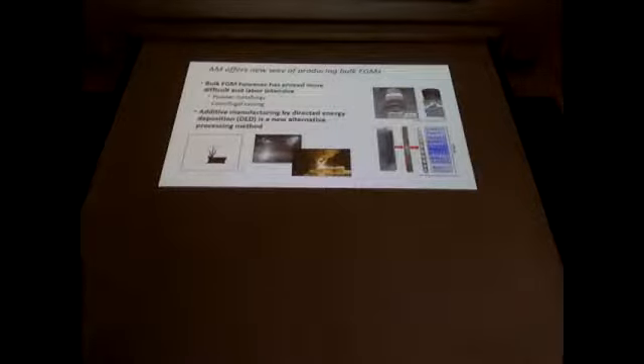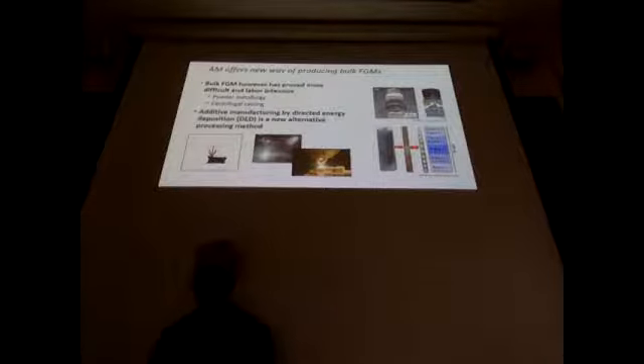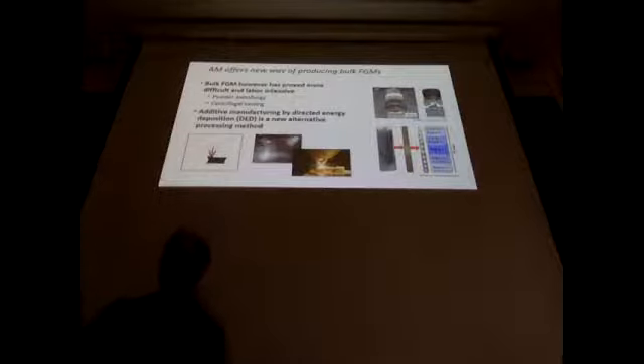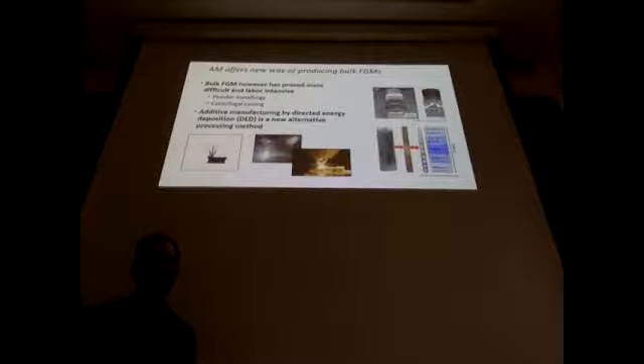So with that, additive manufacturing has become a tool to make these bulk functionally graded materials. Initially, they were done by powder metallurgy or centrifugal casting. Those are difficult processes to get very tight control on your final component. The benefit of additive manufacturing is that since you're dealing with a layer by layer approach, especially with laser direct energy deposition, you control the point where you're depositing material. You can also control the material that you're introducing into that weld pool.